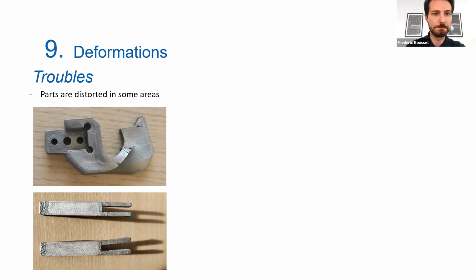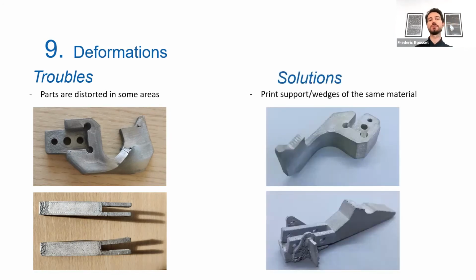For this trouble, the deformation, we have a couple of different deformations. The first one was the twisted parts. We can help this one by printing some supports or some wedges of the same material. As you can see on the bottom right photo, we printed some supports or wedges on the bottom and on the sides of the piece, which helped the piece not to deform. This is the solution that is working quite well that we are using recently. We used it on the top photo as well, but we didn't keep the wedges that we used. And that's all. Thank you.